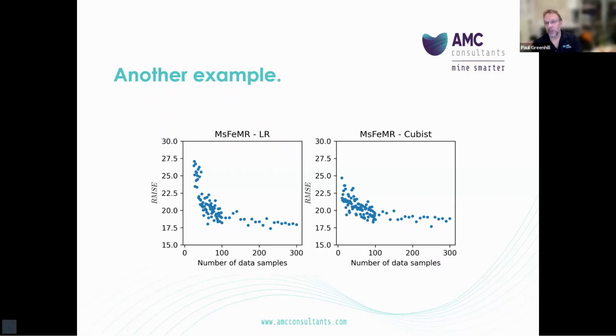There's a clear reduction in the RMSE values as the number of samples in the model increases. Of interest, when this data is compared with the DWI data, there is a clearly different plateau for the RMSE data. So recall for the DWI, those values were of the order of 1 to 2. With this process data, we are talking about RMSEs of the order of 17 to 18, and so on. So we attribute this to the underlying uncertainty in the measurement, and this recovery data has a much higher intrinsic uncertainty than the DWI test data.